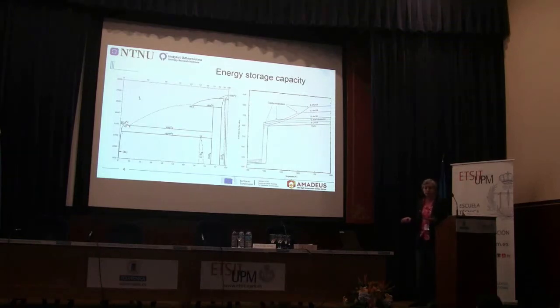So how will the latent heat look for different amounts of boron in our silicon-boron alloy? So here we see the temperature, here we see the enthalpy in the alloy. So the black line here is the pure silicon. So we see the latent heat here. If we are at the eutectic composition, 3% of boron, it will be the green line. So the latent heat here will go from here to here. So that will be the highest latent heat that we will have in this system. Because, for example, if we have 15% of boron, that is the dark blue, we see that the latent heat will be much lower compared to the 3%. So again, it will always be an advantage to have the eutectic composition, not to have a non-eutectic composition.